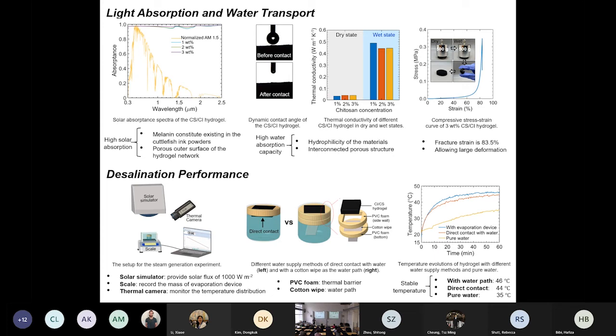One thing I want to show you: the original idea was a direct contact. So we have our carbonized melanin or the cuttlefish ink, the CS/CI hydrogel, directly floating at the water interface. It was a concept. It does evaporate water at a higher rate, but it may not be ideal. Why? With direct contact, you can imagine the top surface serving as a solar absorber absorbs sunlight, and the heat can be conducted to the bottom surface. So it's totally a waste of energy. All of this energy will be dissipated to the water. So this is something we should try to avoid.